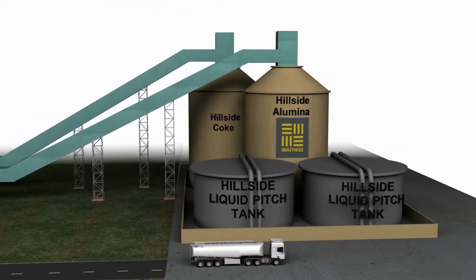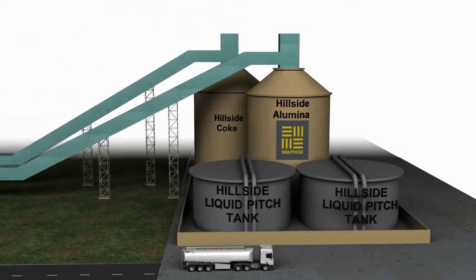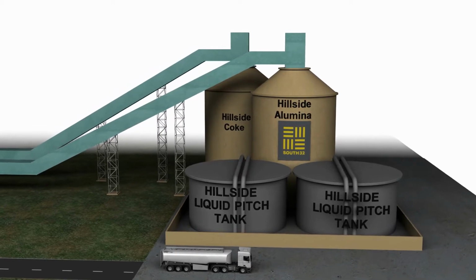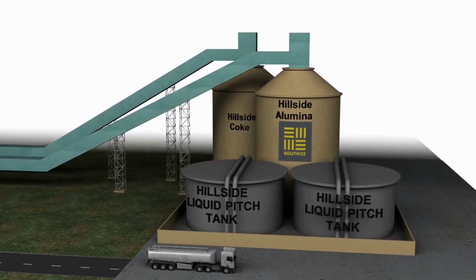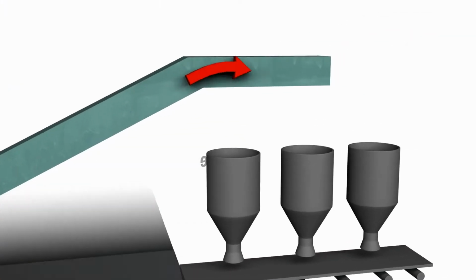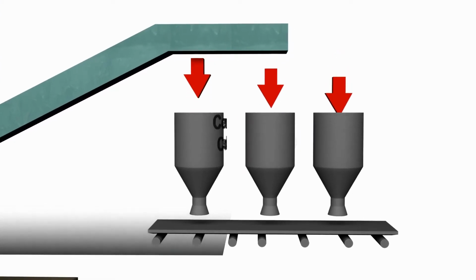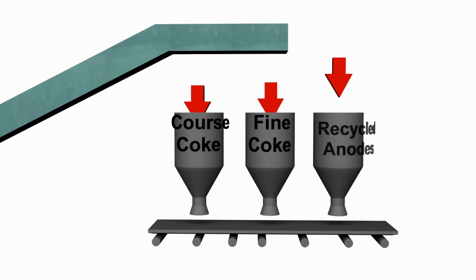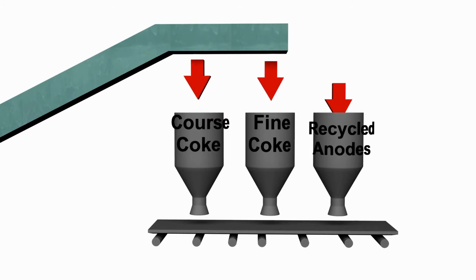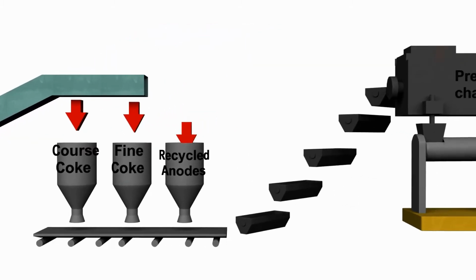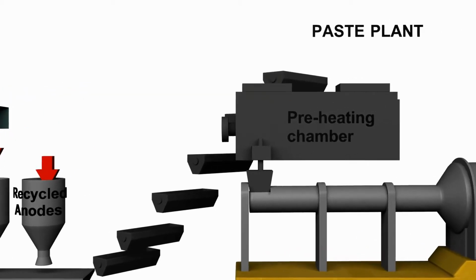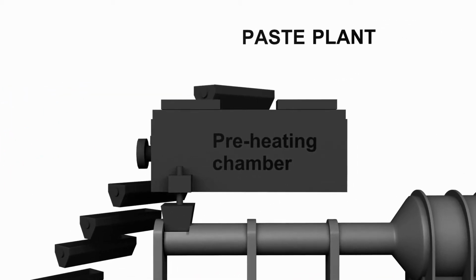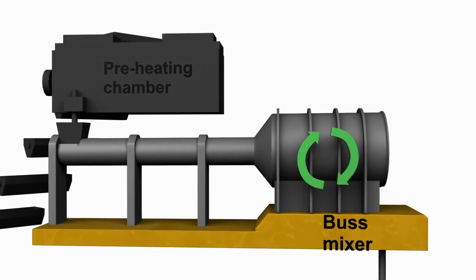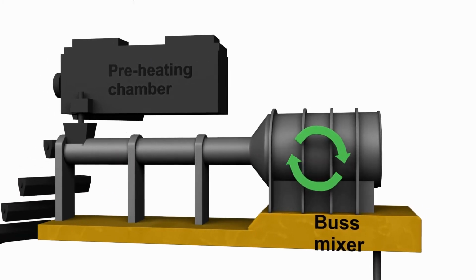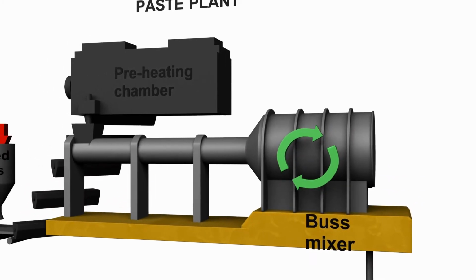Aluminium is produced by electrolysis, and carbon anodes are an essential part of this process. Anodes are made in the following way. Coke enters the paste plant, where it is sorted, graded, and blended with spent anodes, which have been crushed for recycling. The coke mixture enters a preheating chamber via a bucket elevator, after which it is transferred to the Buss mixer, where it is thoroughly mixed with liquid pitch to form a paste.